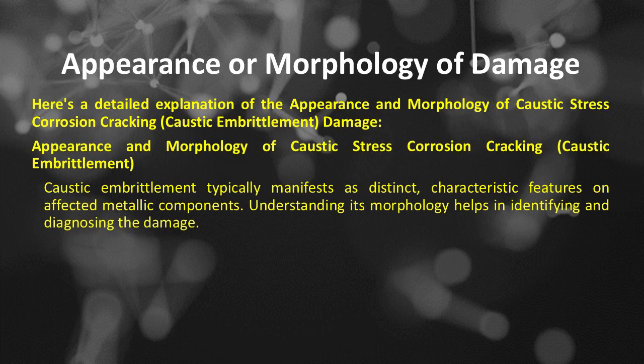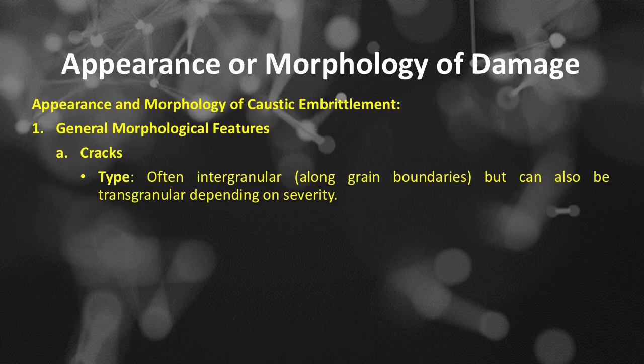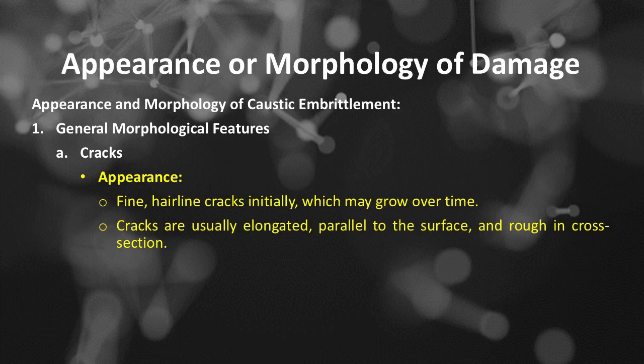Caustic embrittlement damage typically manifests as distinct, characteristic features on affected metallic components. Understanding its morphology helps in identifying and diagnosing the damage. Appearance and morphology of caustic stress corrosion cracking or caustic embrittlement. Number 1 is general morphological features, which includes, number A, cracks, often intergranular, along grain boundaries, but can also be transgranular depending on severity. Appearance of cracks: fine, hairline cracks initially, which may grow over time.